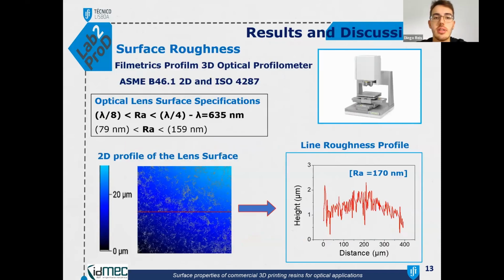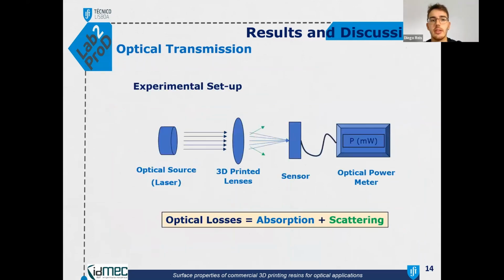And for the results and discussion, the surface roughness was measured by a 3D optical profilometer. The best line roughness that we could get in a distance of 400 micrometers was 170 nanometers, which is a bit higher than the minimum requirements for optical applications with a lambda of 635 nanometers. The optical transmission was obtained through the following setup: the optical source with a laser beam, then the 3D printed lenses, the sensor, and the optical power meter.